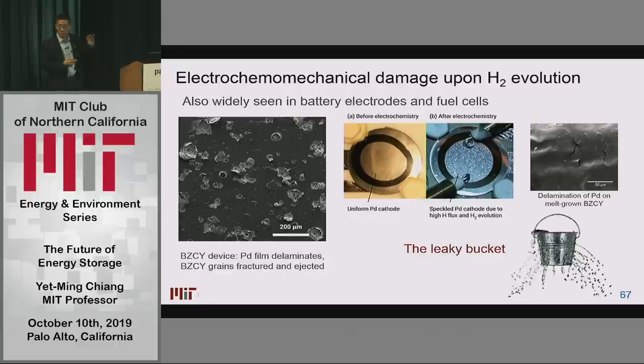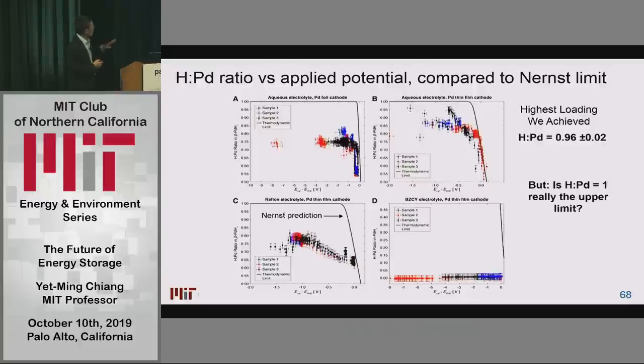What we found is the best way to do it is to make the underlying substrate as soft as possible. This plot shows, on the vertical axis, how much hydrogen we got in. One, at the top, is saturated. The horizontal axis is the voltage that we apply to the device, increasing as you go to the left. The lines there are the theoretical, thermodynamic values that we would get. In every case, we don't reach that line because the bucket is leaking. But we show that we can get very close to the saturated value, 0.96. And we're able to do this to very high precision.